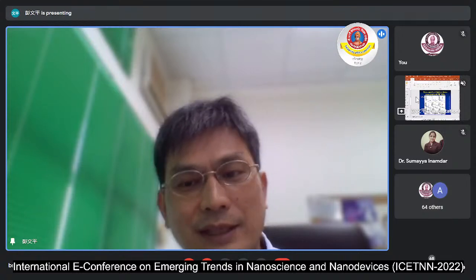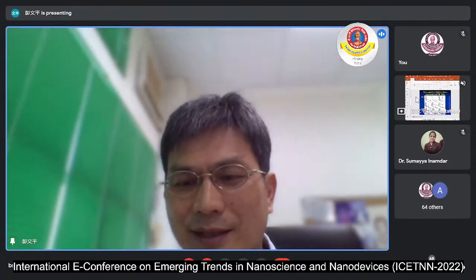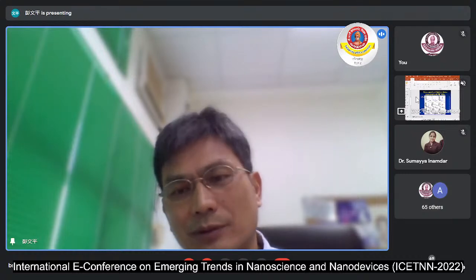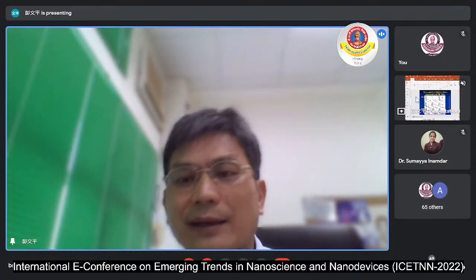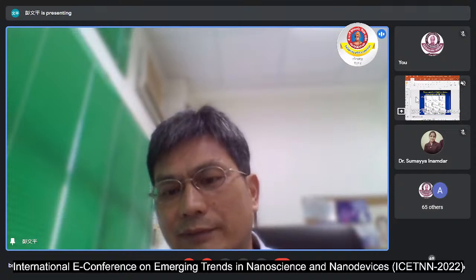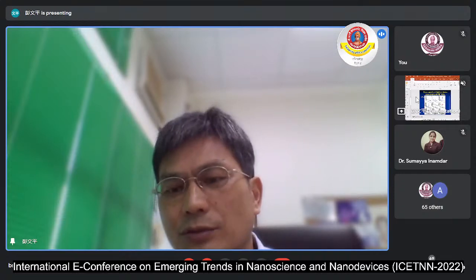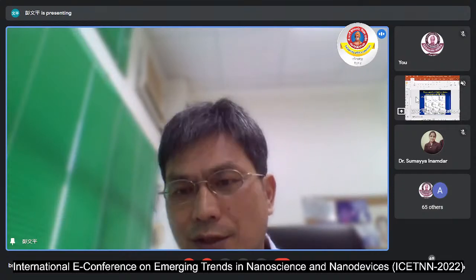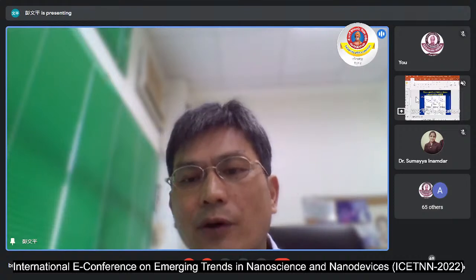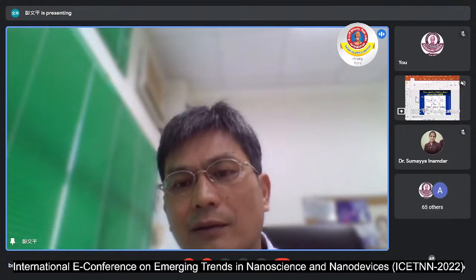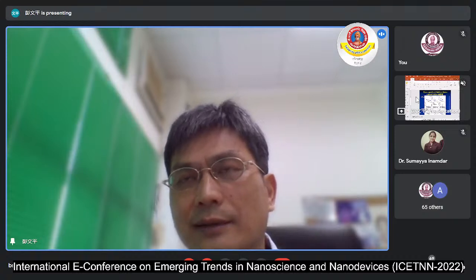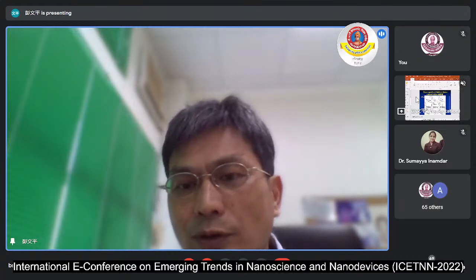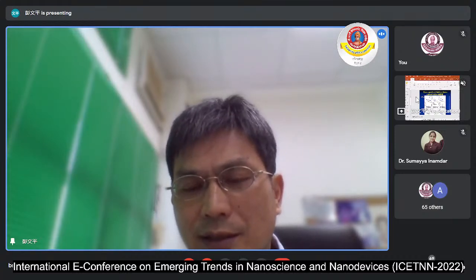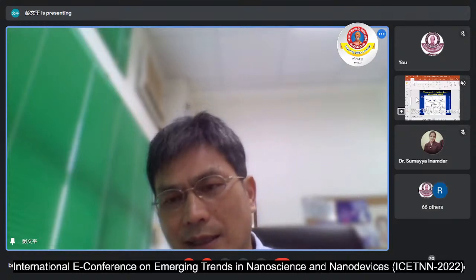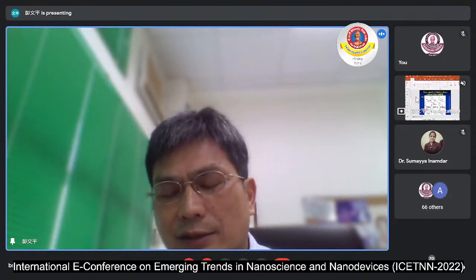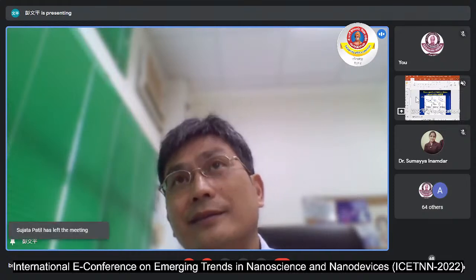So this is the technique using nanodiamond. The advantage is you can do it multiple times, so you know how many molecules are still left there according to your ion signal. So this is HPHT nanodiamond. And for OSDND, we found the initial concentration is not 10 nanomolar, it's 4 nanomolar as compared to HPHT nanodiamond. That means this can be extended to lower concentration, it's not strange, right?